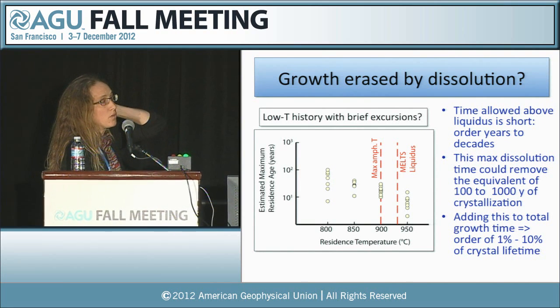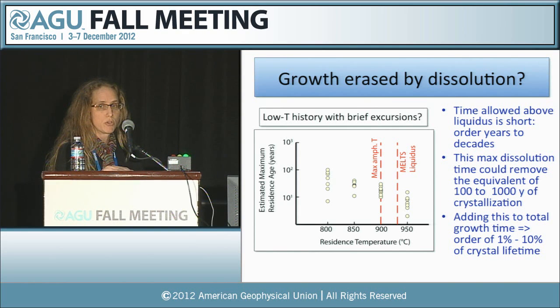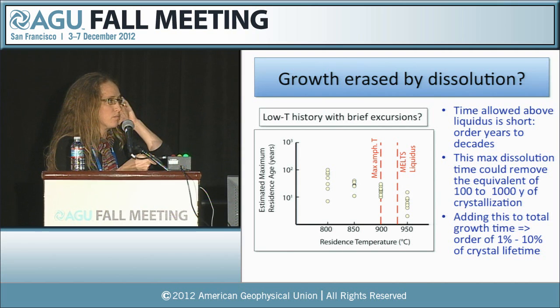All right, now another way you could envision that dissolution might be important is, let's say you had a largely low temperature history for wherever the region is that these crystals were being stored in. You could have brief excursions to high temperature, but because dissolution rates are on the order of about 100 times faster typically than crystallization rates, you could do a lot of damage in a short period of time in terms of these high temperature excursions. However, we can still place additional limits on that. We have a couple of different estimates for where the liquidus for this might be. One from melts.